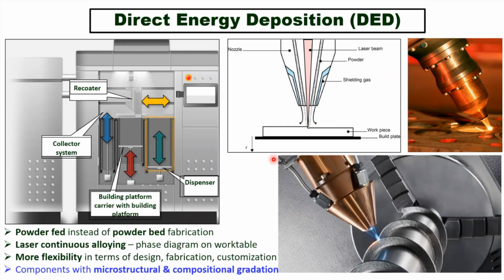But actually, the way you develop the layer is through so-called point or droplet integration. At a time when the beam interacts with the incoming stream of powders, it melts only a small volume, which gets deposited. As you keep moving this over a surface, it forms a line. If you integrate a number of lines on the same plane, you make a layer, then you lift the focus by a certain amount and go to the next layer. That's how you make a 3-dimensional product.